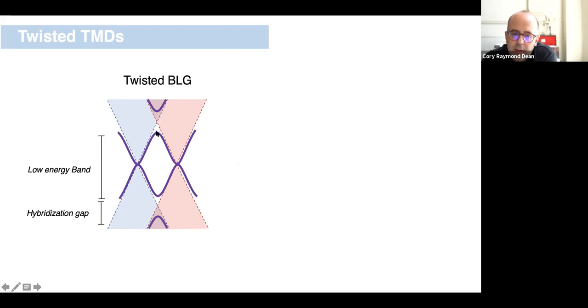And the overall width of this low energy band in this cartoon picture is just fairly simply a function of how physically separated these bands are in K-space. So that relates to the twist angle and how big this hybridization gap is. So basically the size of the hybridization gap matches the energy scale that corresponds to the point of crossing of these bands to the charge neutrality point. If those two are equal, then you get the flattest band possible. And that gives rise to this magic angle at which there is this very flat band defined at a very precise angle.